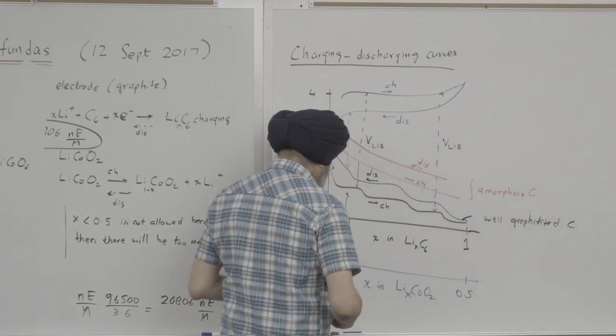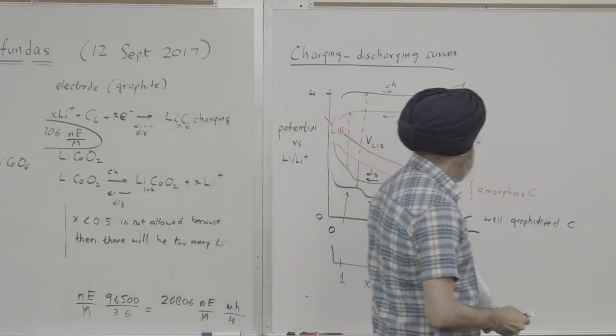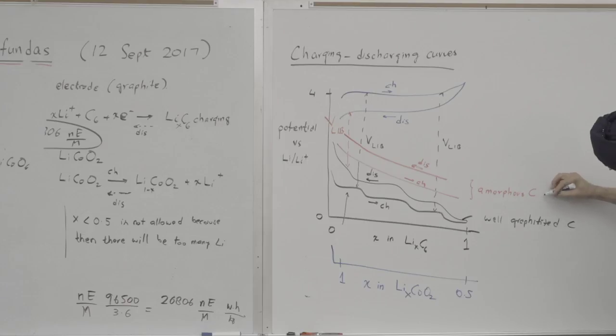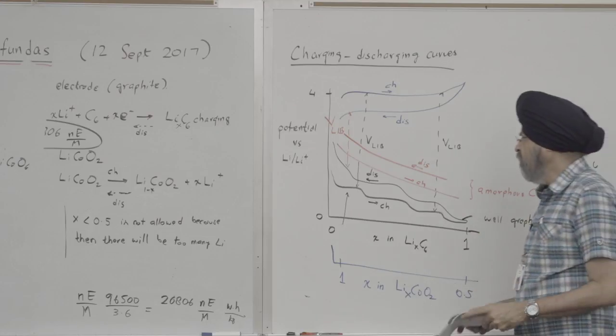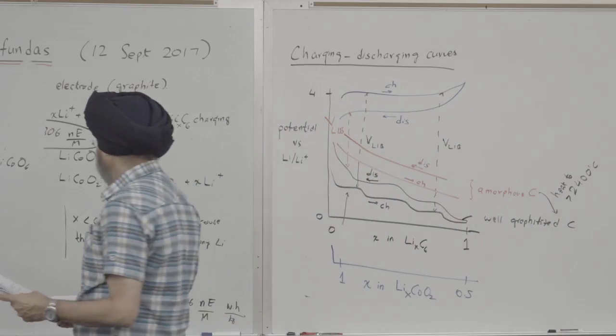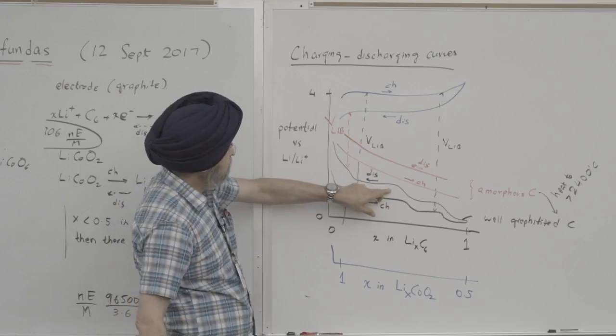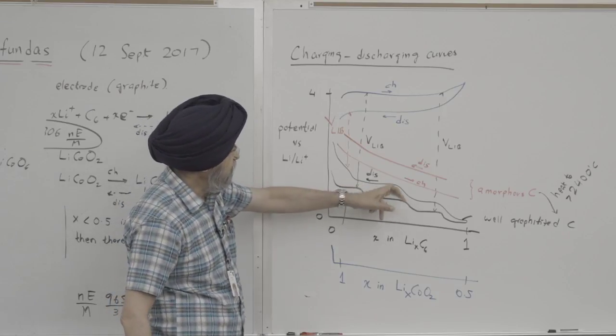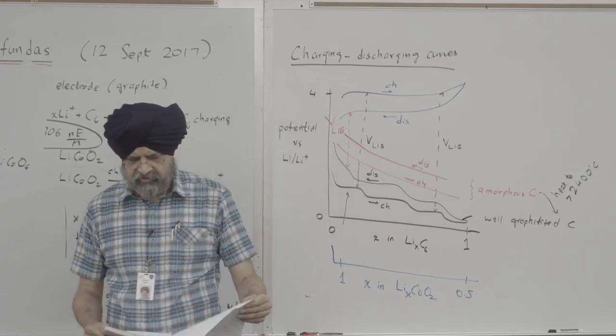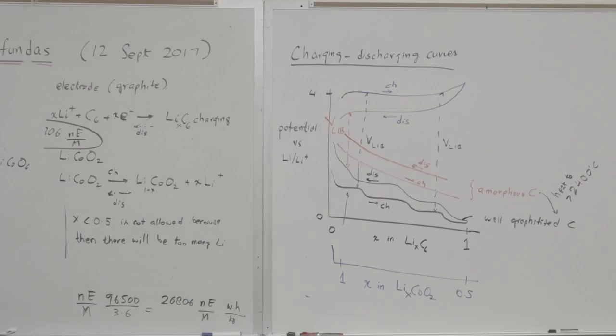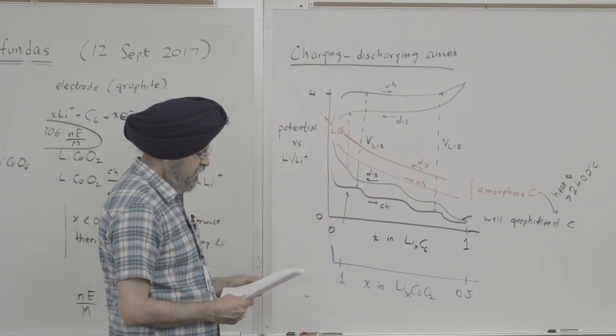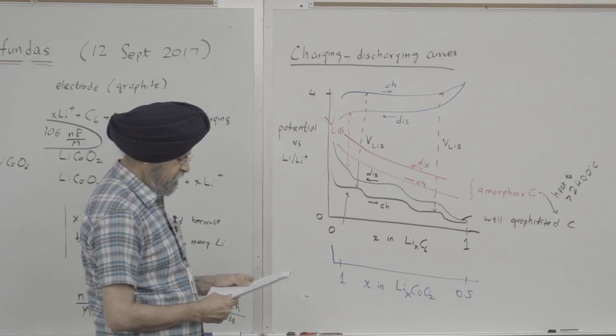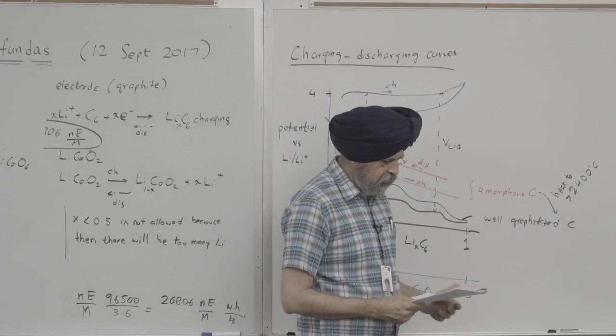And to go from amorphous carbon to well graphitized carbon, you need to heat to greater than 2400 degrees centigrade. So you get this well-formed graphite. And the reason you have this hysteresis, one factor is mechanical stresses. When you go from charge to discharge and back, you have mechanical stresses you have to overcome. So basically, you want as perfect a graphite as you can get. And you can get that by heating up to more than 2400 degrees.